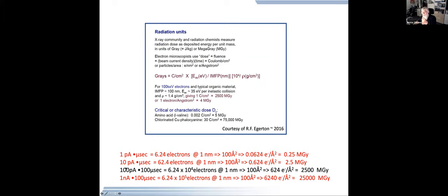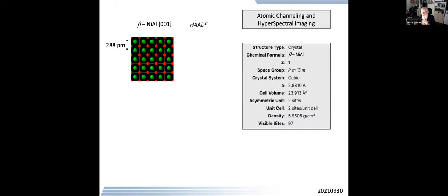I tend to do most of my experiments nowadays in the range of 10 to 100 picoamps and a range of a few microseconds to upwards of a few hundred microseconds. So the kind of dose that we're using, depending on the size of our probe, is somewhere in the order of a few electrons per square angstrom to several thousand electrons per square angstrom. Now, material scientists are spoiled. We're spoiled because we can look at metals and ceramics and put a pretty large dose on them.